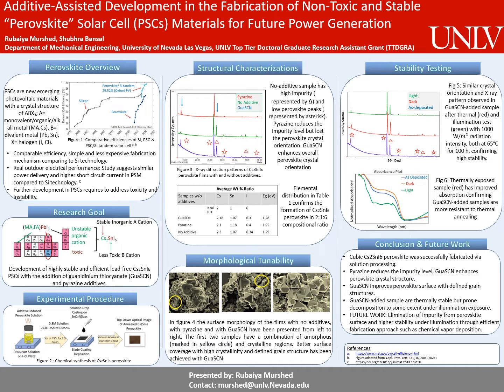organic cations, tin as a less toxic B cation instead of the toxic lead cation, and iodine as a X anion to fabricate dicesium tin hexaiodide perovskite and study the influence of guanidinium thiocyanate and pyrazine additives in the improvement of the photovoltaic properties of this perovskite composition.